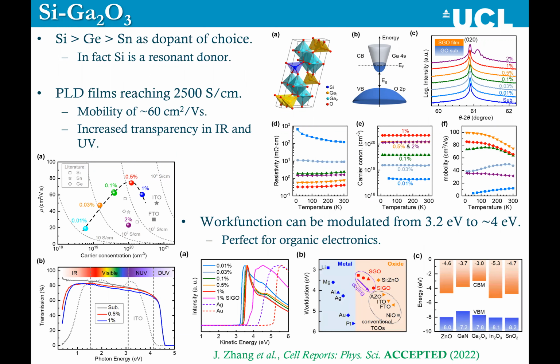And even better, we could modulate the work functions of the systems from about 3.2 eV to about 4 eV, meaning that they're actually perfect for organic electronics, because the typical TCOs have work functions from about 4.5 to 5 eV, which means they're not ideally placed for a lot of organic semiconductors. So this now brings this high conductivity, high mobility, brings these systems more in line with being used in organic electronics.